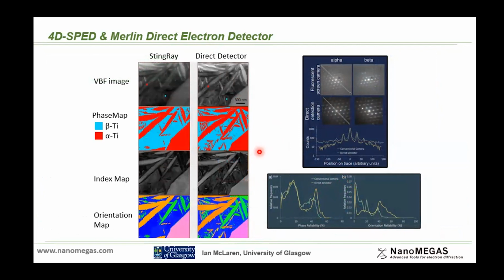You can see even from the virtual bright field image that this image is sharper, so we have better contrast and it is better quality. And of course, also in the phase mapping and the orientation mapping, we can see much more details when this direct detector is used.